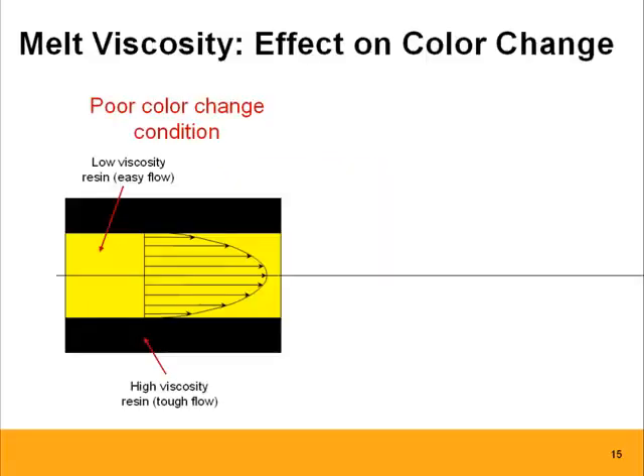Now we'll move on to melt viscosity and the effect on color change. So first, a not so good condition. If we're trying to purge out a high viscosity material, a tough material, with a lower viscosity material, an easy flow, you see what's happening. The material on the inside just doesn't have the strength to push out the higher viscosity material.